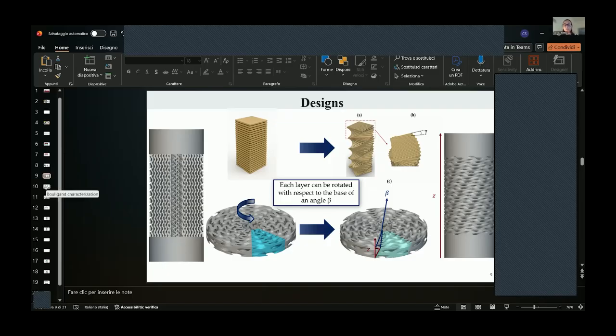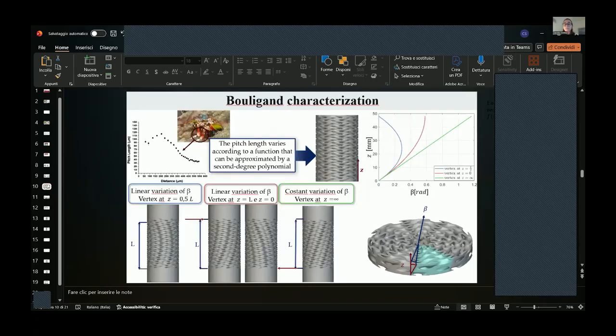But since beta is a function, the question was which kind of function it should be. And we went back to look in nature, and we found that for some specific mantis shrimps, in which the club is made of a Bouligand of fibers and it has to withstand high cycle loads, the pitch length of this Bouligand varies according to a function that can be approximated to a parabola, or a second order degree polynomial. So we imposed beta as a parabola, a second order degree polynomial, and we developed 4